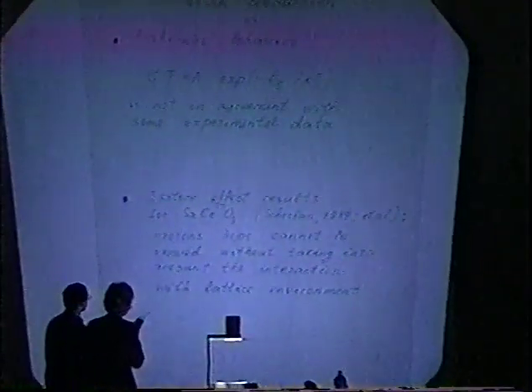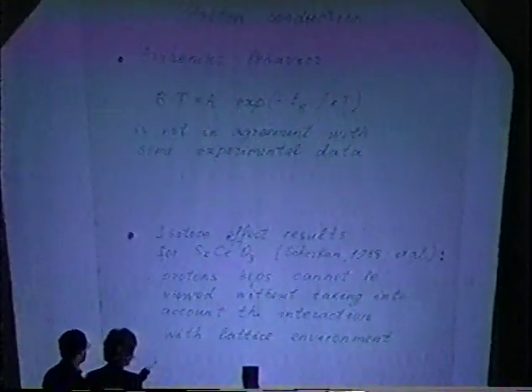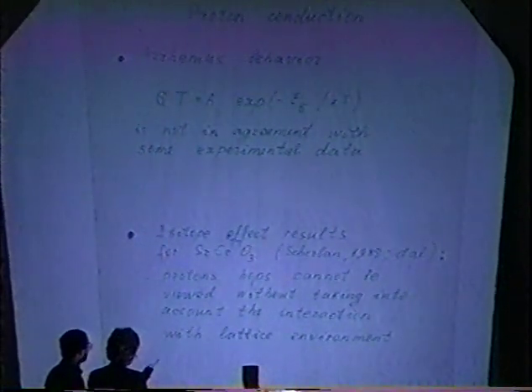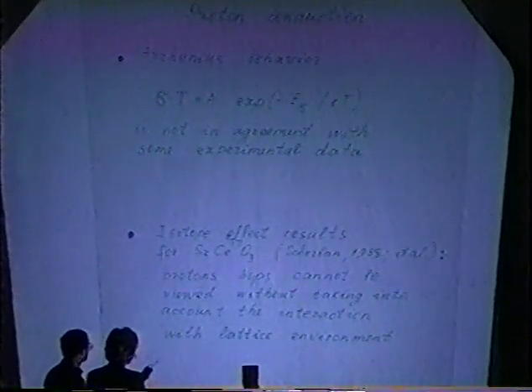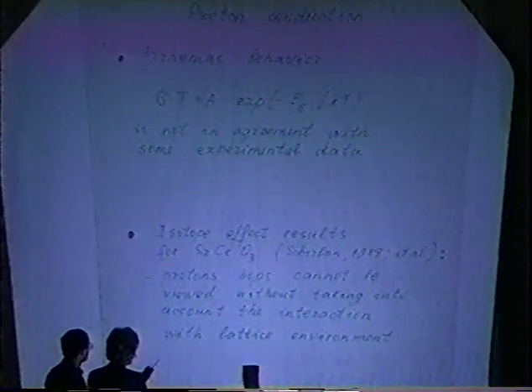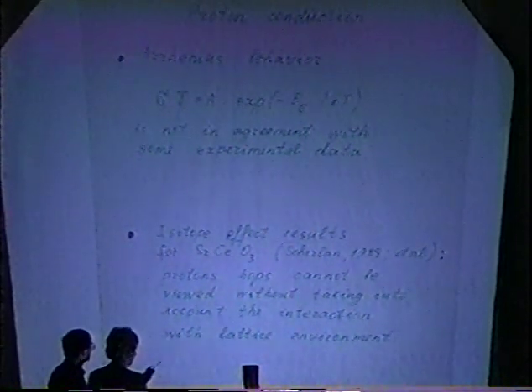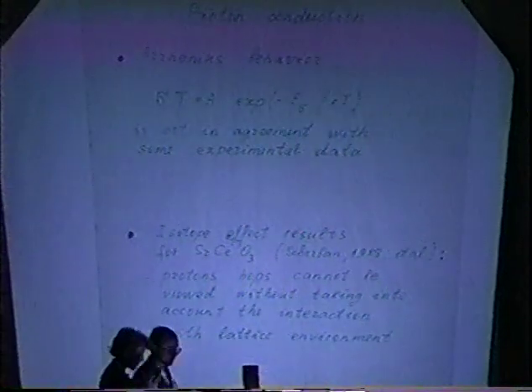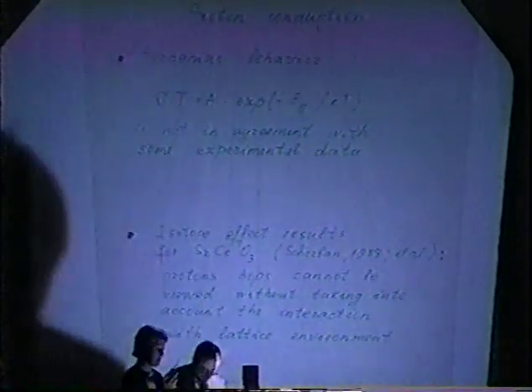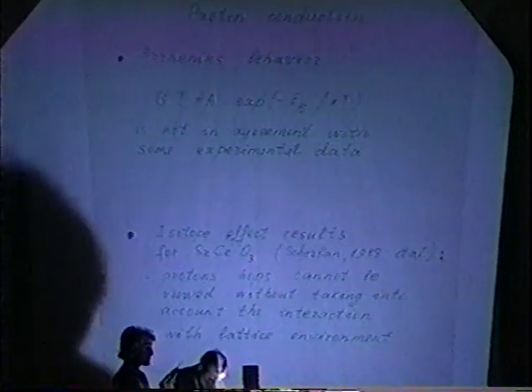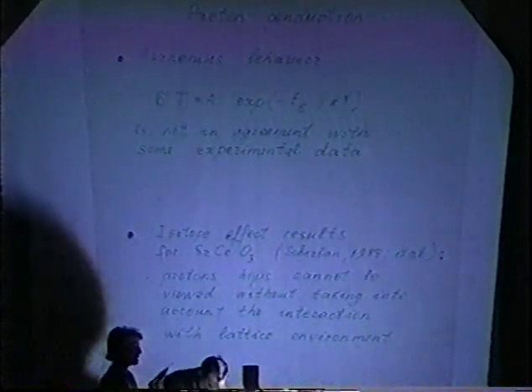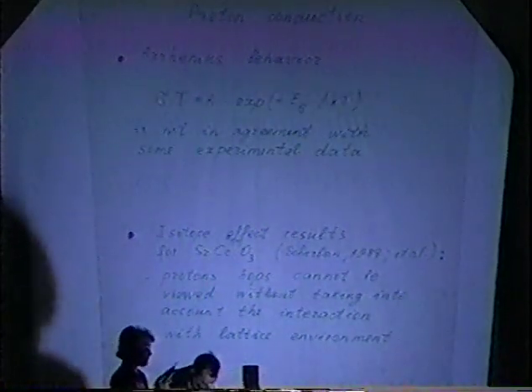Here are the isotope effect results for strontium cerium oxide. These results show that proton hops cannot be viewed without taking into account the interaction with the lattice environment. And maybe this nuclear interaction may lead to anomalous effects.